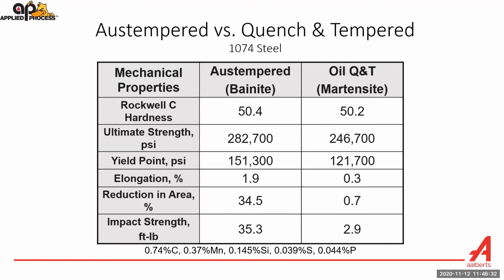Let's jump into some of the mechanical properties. This is what a lot of engineers are interested in as well. This is a 1074 steel, Austempered, bainitic, versus oil quenched and tempered martensitic at the same hardness. The bainitic steel exhibits a higher tensile strength, a higher yield strength, and look at the difference in elongation. That is one of the key things. It stretches before it breaks about 6 times the amount of an oil quenched and tempered steel at this hardness. And that results in a dramatically improved impact strength, energy absorption.